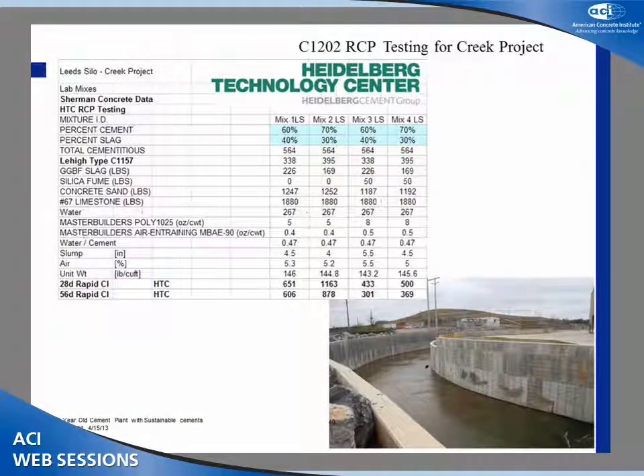We did a lot of RCP testing, and we are in the very early stages of developing the mix. We looked at using the slag, and we also looked at using silica fume. It's interesting here that to go from 30% slag to 40%, look at where your RCP numbers go. So it's a huge addition. Your RCP slag does very well with the RCP, right? Same thing with our silica fume over here.